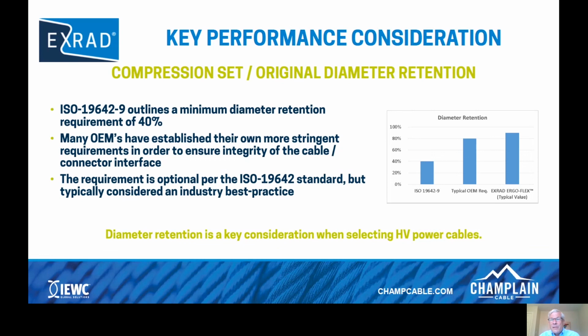Compression set and original diameter retention are really opposites of one another. The compression set is how much the deformation remains permanent versus original diameter retention, which is a measurement that is used by our ISO standard 19642-9, which outlines a minimum diameter retention of 40%. Now, what some of our connector manufacturers have discovered is that number is not good enough, so some OEMs have established their own more stringent requirements in order to ensure the integrity of the cable connector interface. 80% is an example of a typical OEM requirement. This requirement is optional per the ISO 19642 standard, but it's typically considered an industry best practice.